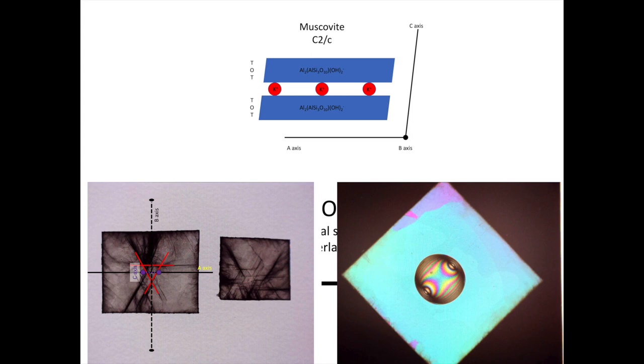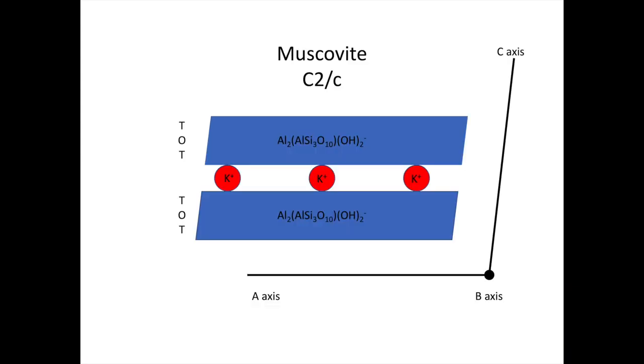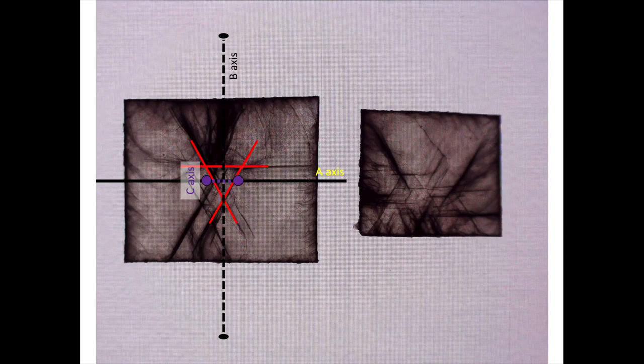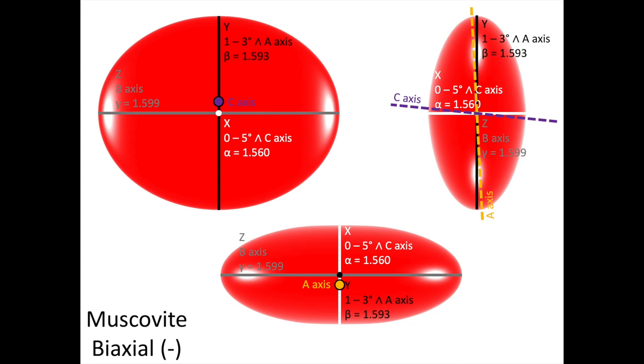All right, let's go through a brief review of what we've done today. We talked about the chemistry and structure of our muscovite mica and how our muscovite is a monoclinic mineral. We talked about how the cleavage of muscovite is a very prominent crystallographic feature. However, you can also generate a percussion figure which gives you additional crystallographic information for your muscovite. We then investigated the optical indicatrix for our muscovite, which is a three-dimensional representation of the refractive indices of our muscovite. For our monoclinic minerals, the axes of our optical indicatrix and our crystallographic axes do not align perfectly, and for muscovite, only the B crystallographic axis and the Z direction through our optical indicatrix line up. However, the C crystallographic axis isn't too far away from our X direction through our optical indicatrix.